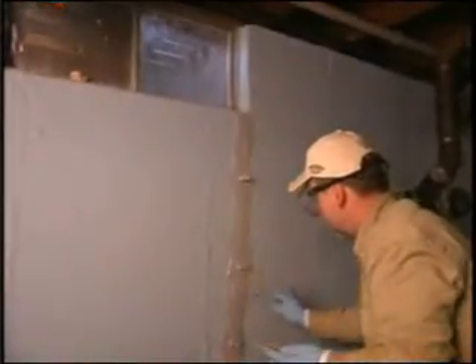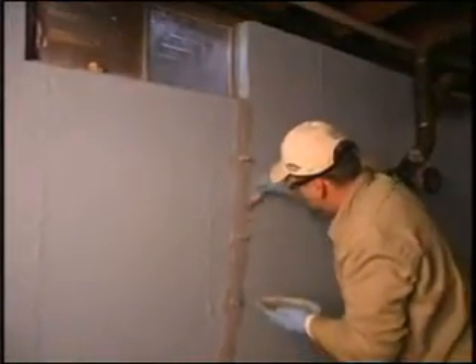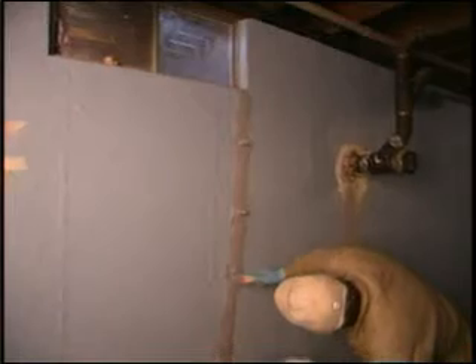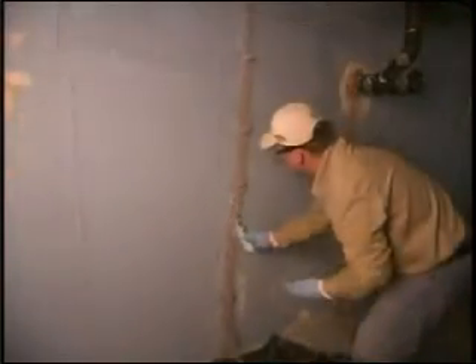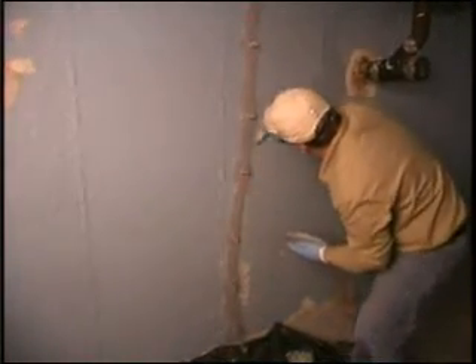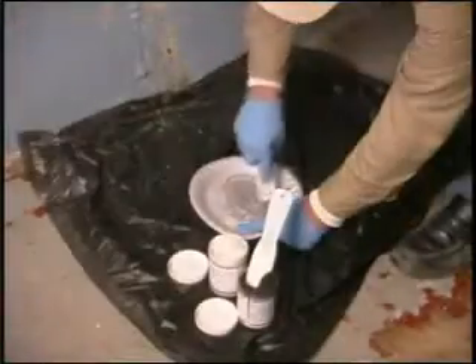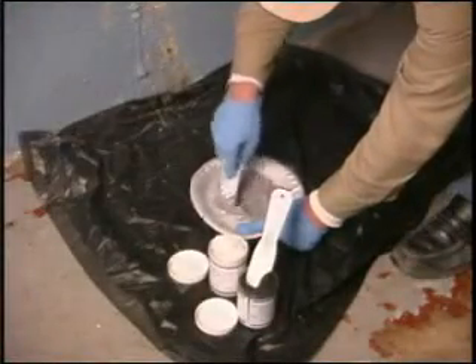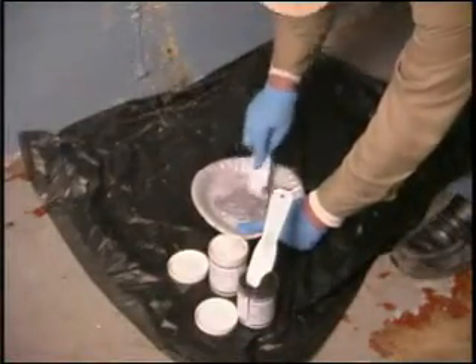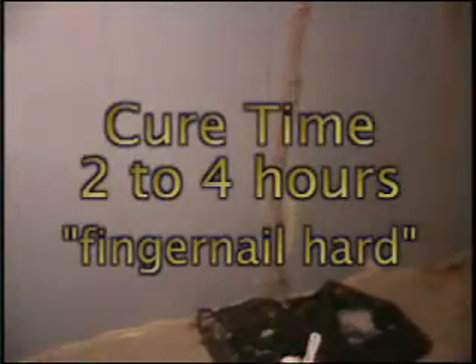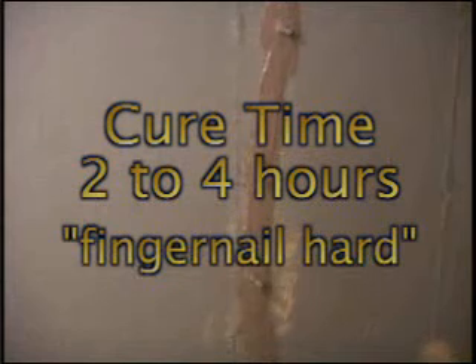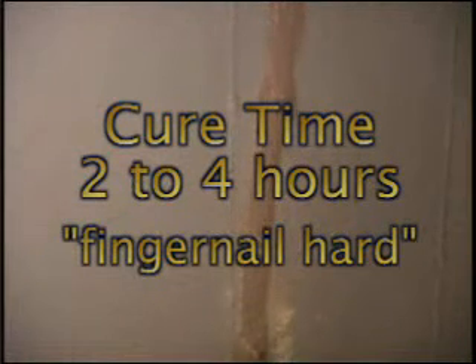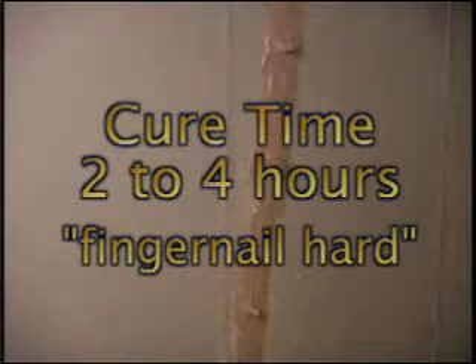Make sure to apply sufficient amount of extra epoxy around the base of the ports. Do not work the epoxy into the crack, just paste over the surface. Expect to use 16 ounces, the total amount provided for an 8-foot crack. Let the surface seal and port adhesive cure before beginning injection, about 2 to 4 hours, or until fingernail hard. We do not recommend to wait overnight.